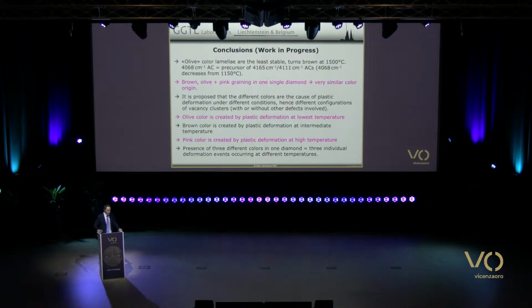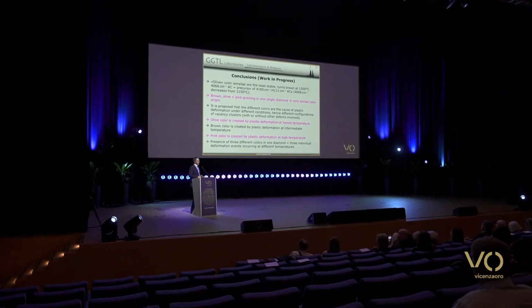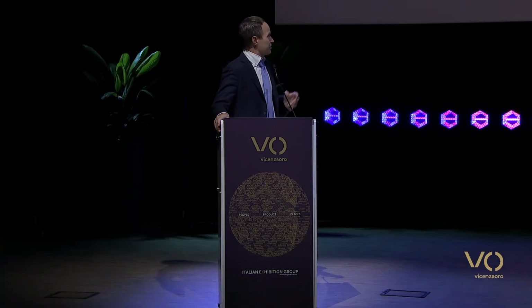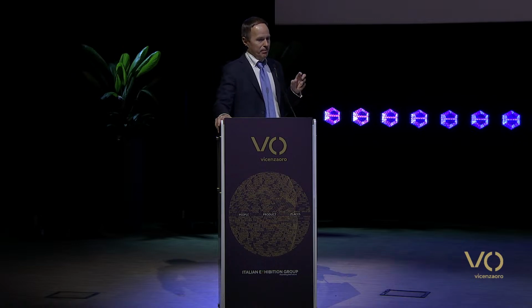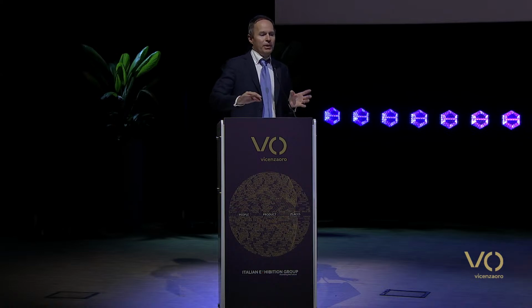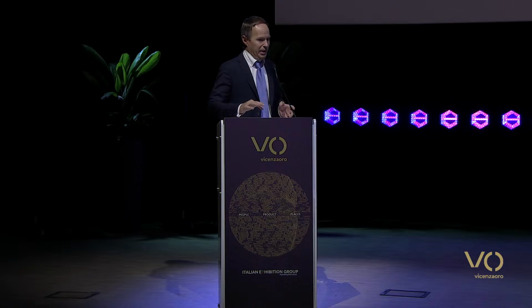So, conclusions. Looking at all the data, we came to these most important conclusions. First of all, we have brown, olive, pink grading in one single diamond. It's obviously a very similar color origin. We propose that the different colors are caused by plastic deformation under different conditions, because that's the only way to explain it. We can't explain a different color origin; it's just formation at different conditions. What's being proposed is that the three colors are caused by different configurations of vacancy clusters with or without other defects involved. That's not quite clear yet.